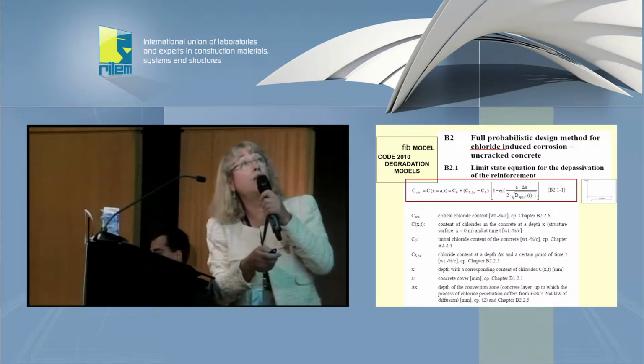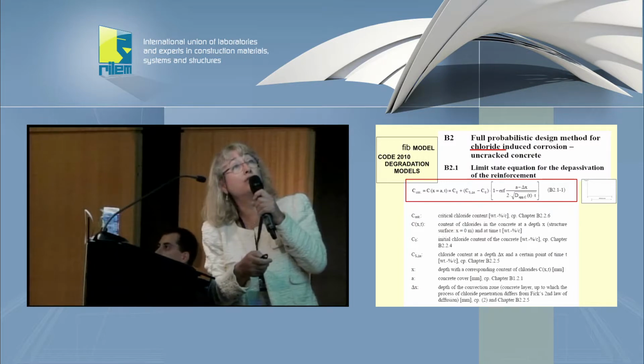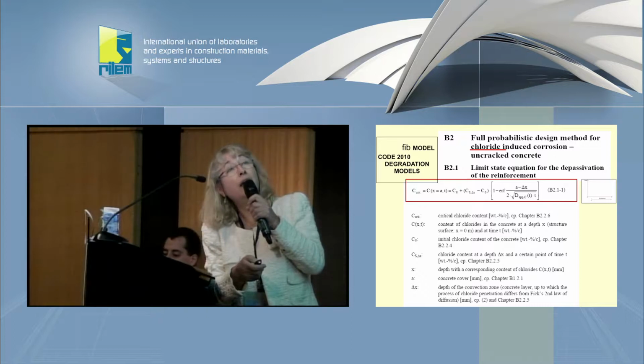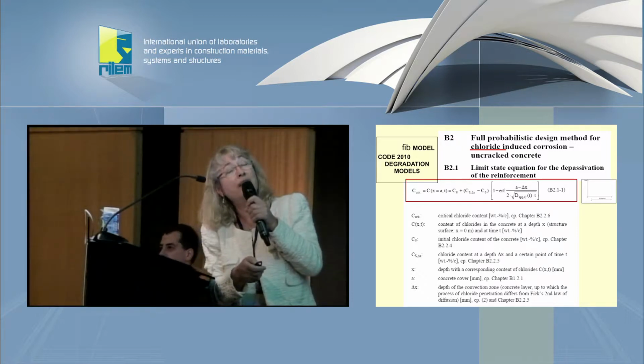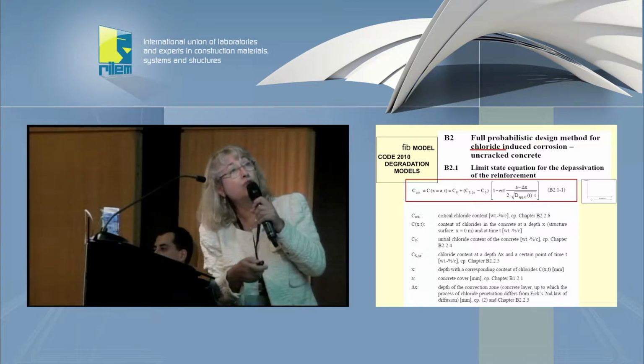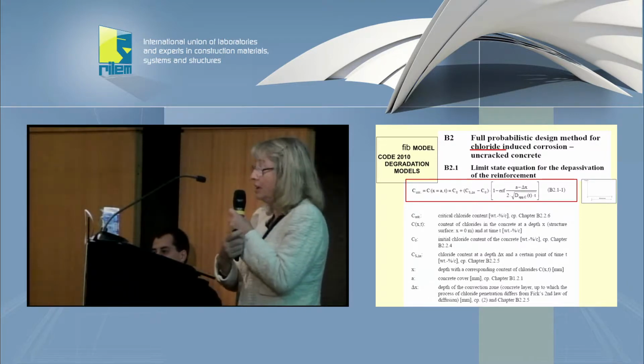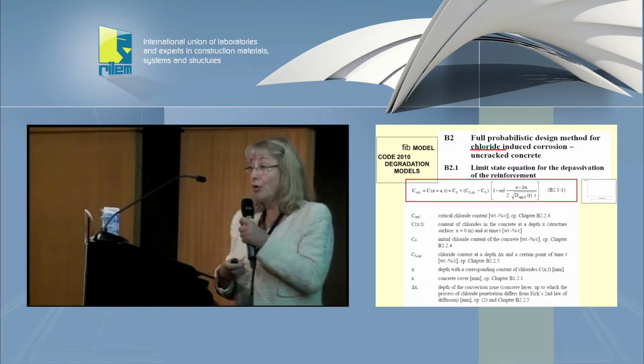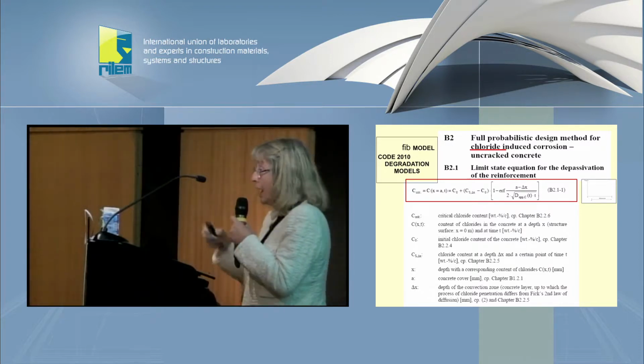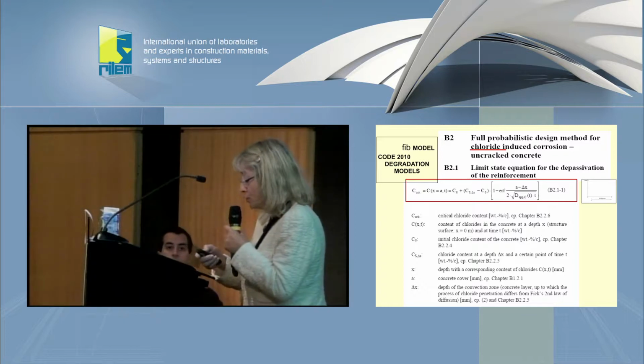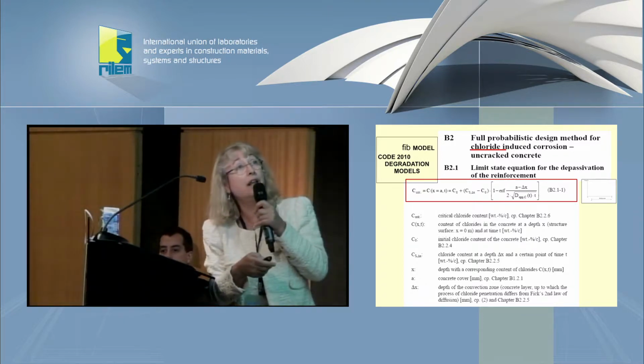Regarding the chlorides, it was taking the error function from Fick's law, and the only change we introduced, at that time we were also members of the RILEM TC that was discussing the influence of the factors, is the convection zone, in order to take into account the case when the profile has a maximum. The other parts are the same. Also, there is an aging factor that is not in this equation, and also the influence of temperature. I will concentrate on chlorides because it's the most common model that is used.